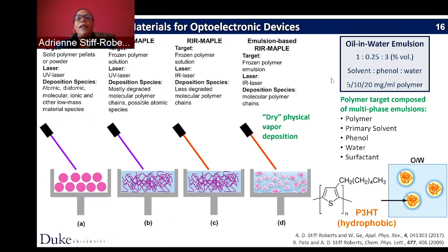So what we developed in my lab is emulsion-based resonant infrared matrix-assisted pulse laser evaporation, RIR-MAPLE. And that was really driven by the fact that we did not want to use a free electron laser. So instead, we used an erbium-YAG laser that has a peak wavelength at 2.94 microns. And that erbium-YAG laser energy is resonantly absorbed by the vibrational modes of hydroxyl bonds, the OH bonds. And so water has two OH bonds, and so water can resonantly absorb this laser energy very well. Now, most of these conjugated polymers that have those semiconducting properties will not dissolve in water. So they dissolve in nonpolar solvents. That means we had to develop a target solution that could resonantly absorb that laser energy, which is how we arrived at using emulsion.